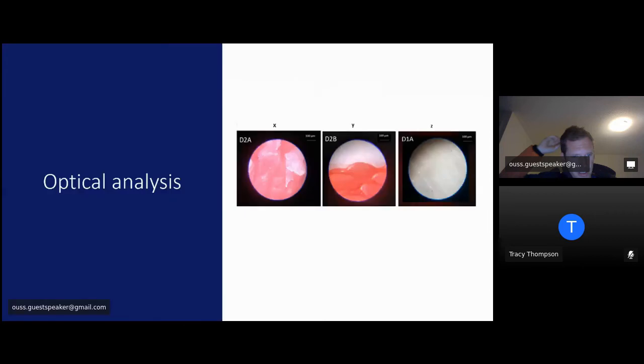There's the optical analysis. So this is a really interesting one. D2B is a combination of 50% recycled material. The white material is actually good new material, and the red, or it looks more pink there, is the older material that's been reused. So as you can see, it's coming out in globules, and it's definitely not straight. D1A is very straight, but D1A is new material. And it's coming out perfectly.